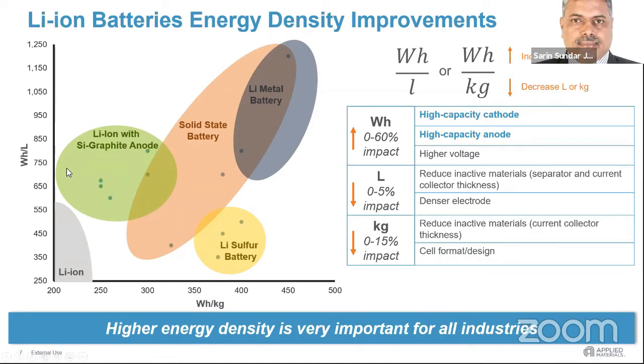In this chart on the left, you can see we have charts only from 200 watt-hour per kg. Most of the batteries that you get in India today are less than 200. For most LFP batteries at cell level, it could be about 170. At pack level, it is about 110 or even less. And even for NMC batteries, most of it is about 250. When it becomes pack level, it comes to less than 200.